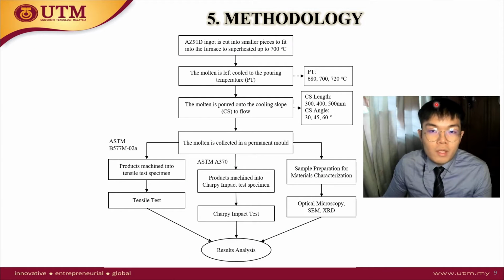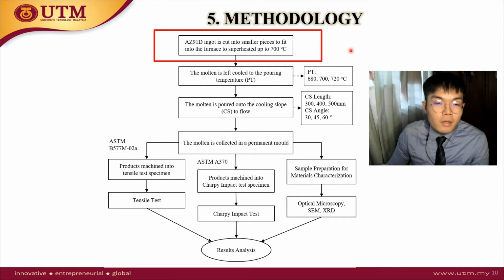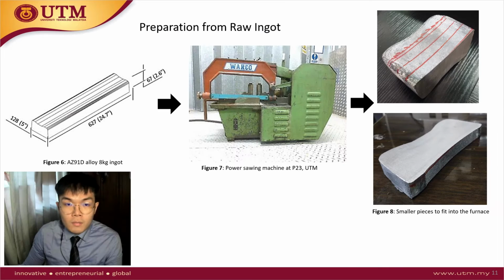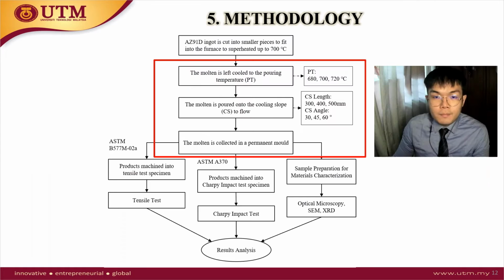And we move on to methodology. The first step is to cut the AZ91D ingot into smaller pieces to fit into the furnace. So from this 8 kg AZ91D ingot, we cut using a power sawing machine at P23 UTM, into smaller pieces to be able to fit into the furnace.